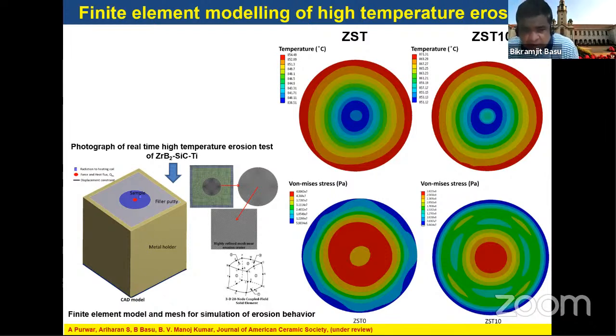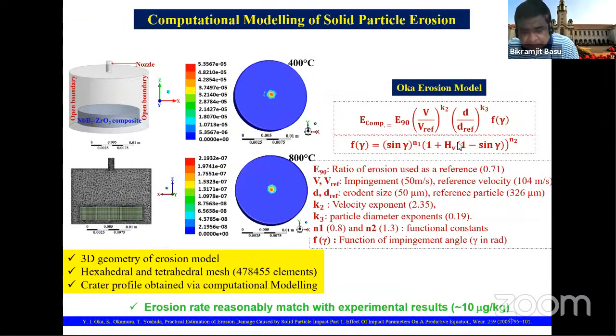And this is the result of the finite element model, to show you what the stress level is here. Remember, this is 10⁷ Pascal. So you have to see it as 10 megapascal multiplied by 4.9. So almost 50 megapascal stresses are being generated around the erosion crater in the two different types of materials that we have investigated.